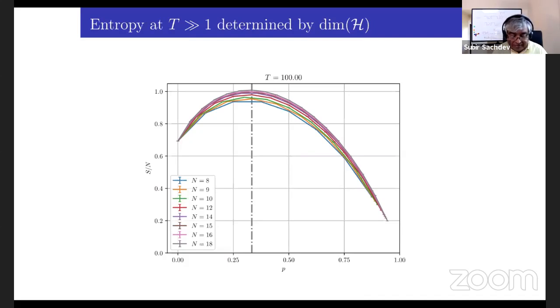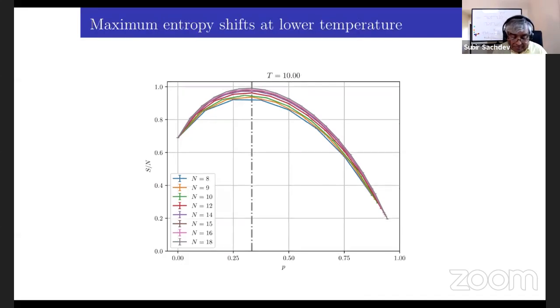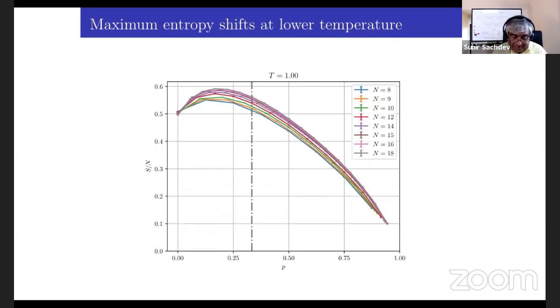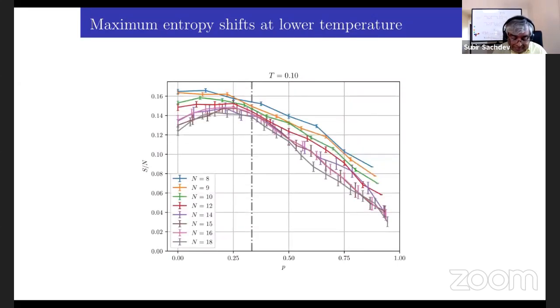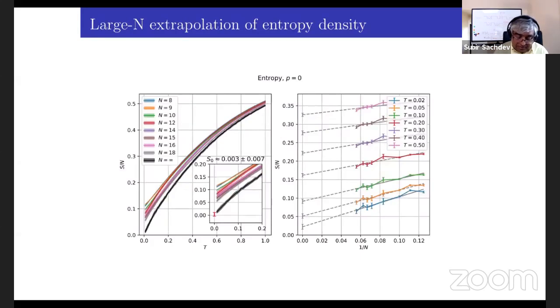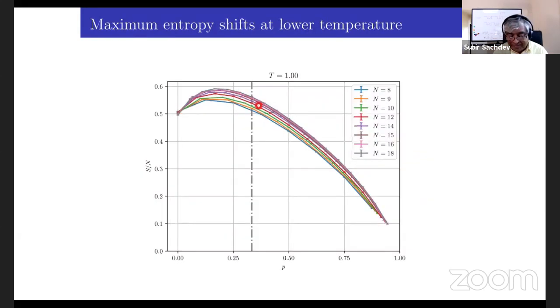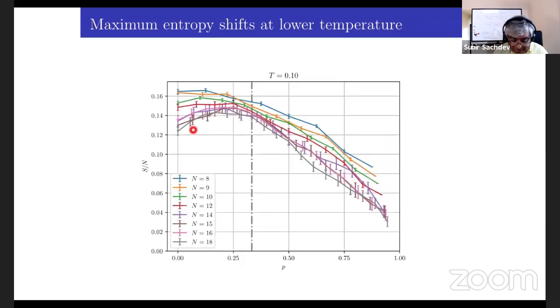Okay, so now what happens as you lower the temperature? So now we go to T equals 10, T equals 1, 0.1. Yeah, that's about as low as you can go. And so certainly what you see is that there is still a very nice maximum in the entropy, but at somewhat lower doping, 0.2 to 0.25. If you go even lower, well, it's hard to tell where it is. And that's, at least qualitatively, what we wanted. We want a maximum in the entropy right near the critical point, because that's where the quantum chaos and the black hole physics of the SYK critical point will kick in.